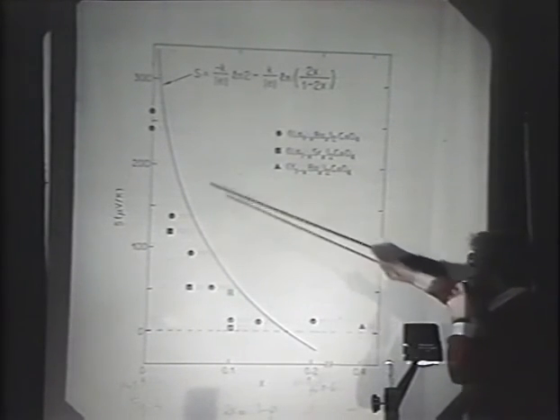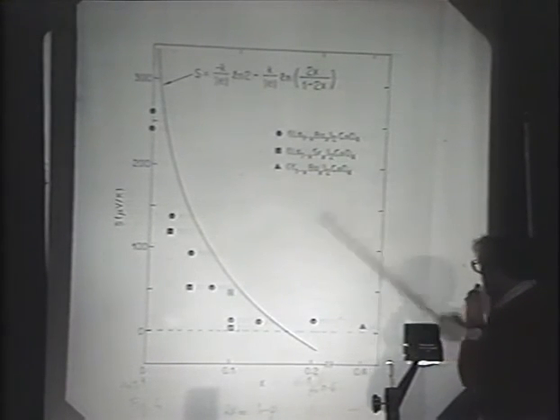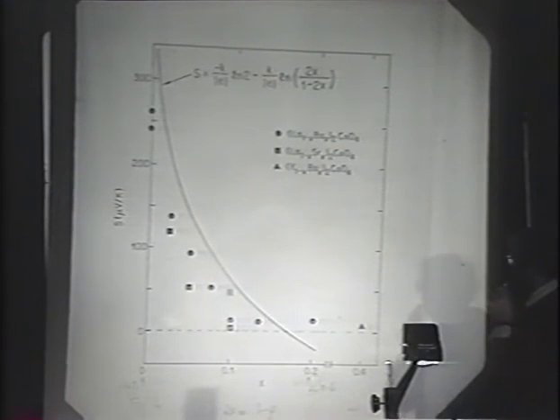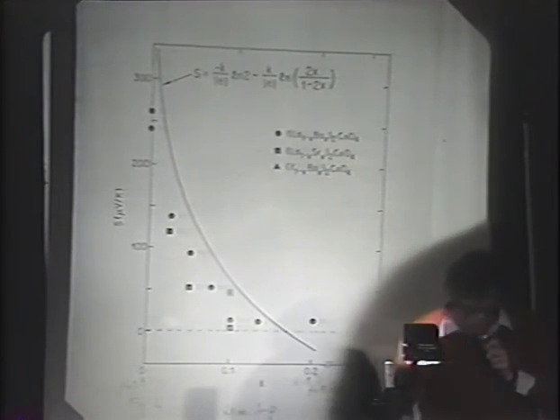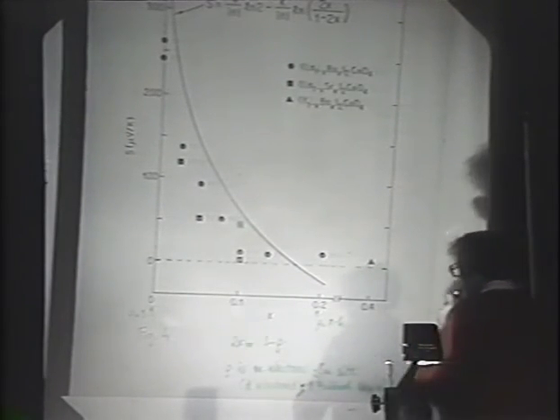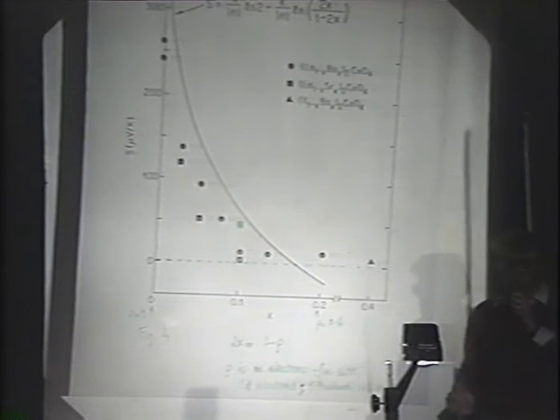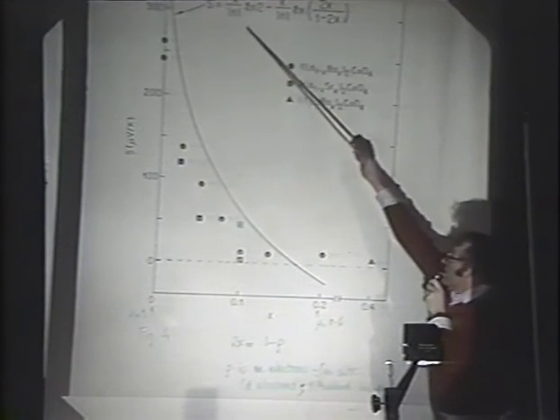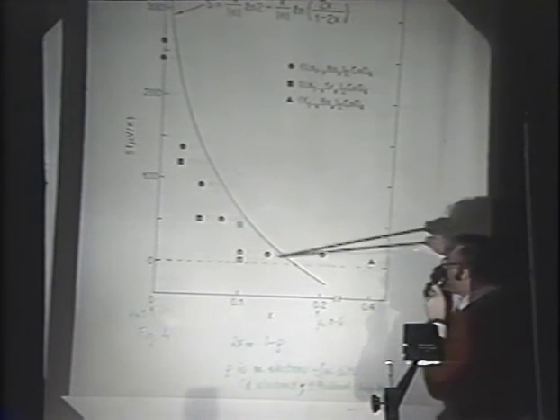So this is a plot then for 3 different compositions of the room temperature thermoelectric power versus X, where X is determined from the weighed amounts of material. And the point I'm trying to make, this solid line is this theoretical formula where you say that you start off with 1 copper d electron per site, and as you add barium or strontium, you're gradually removing electrons from this 1 copper electron per site. And we think as a first approximation, this line, which doesn't contain any adjustable parameters, shows a reasonable description of our thermal power data up to about x equals 0.1.